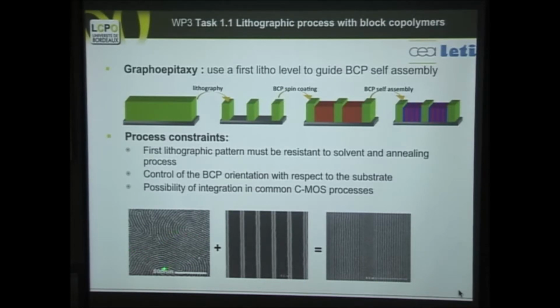So here, at the nano level, you have a surface that was patterned with classical lithography, the 193 resist, and when we put the film of the copolymer inside these edges, then you see that the cylinders are parallel in this case. And we can eventually adjust the surface treatment in between these ranges here, and then the cylinders can be perpendicular. So here I show you that we can now make a feature of approximately 100 nanometers, and make nano features inside, each one 10 nanometers, with the simple process of adding a thin film on it.